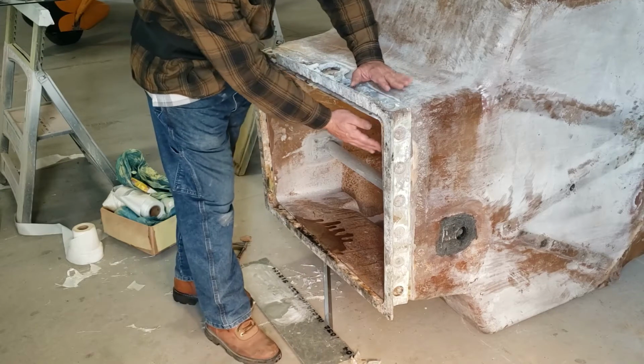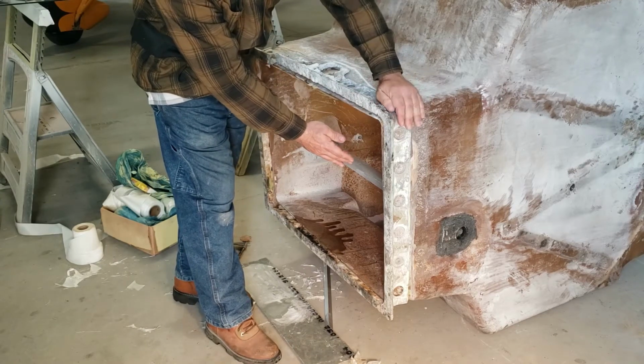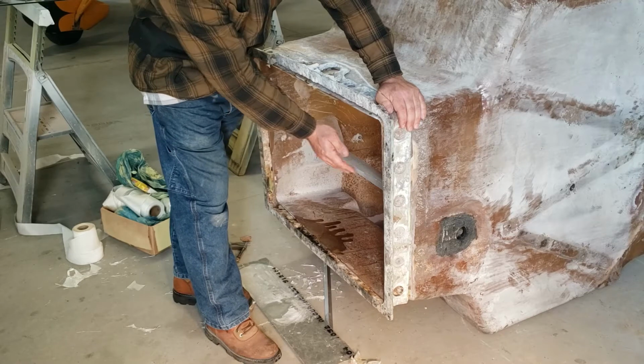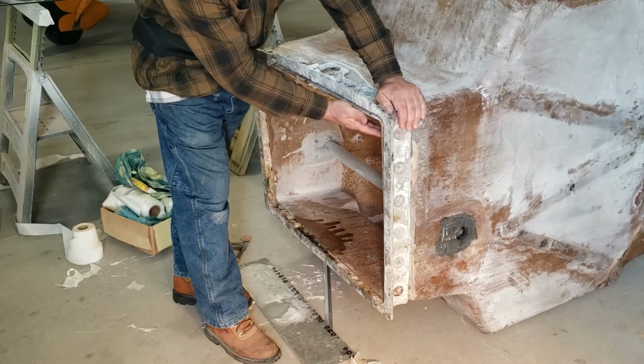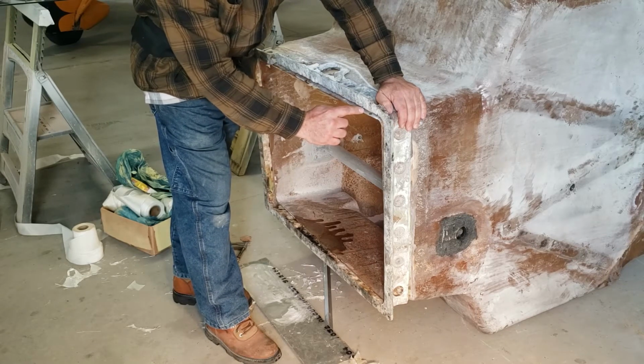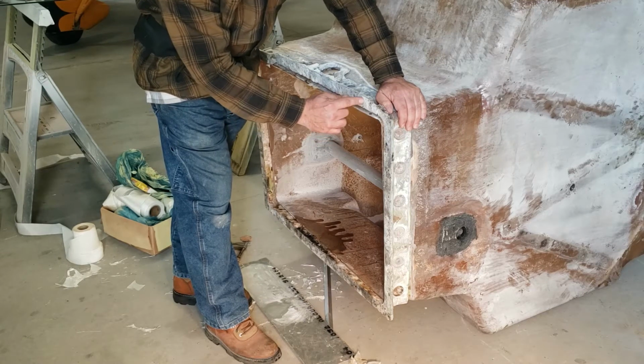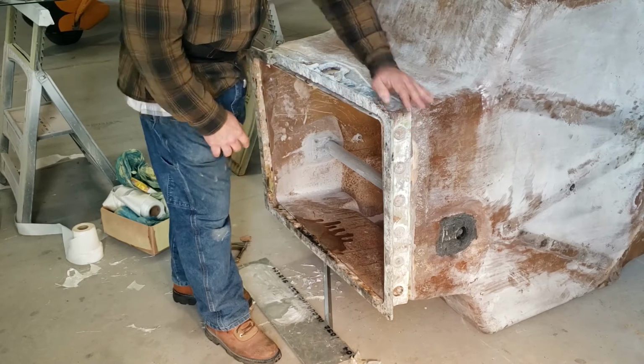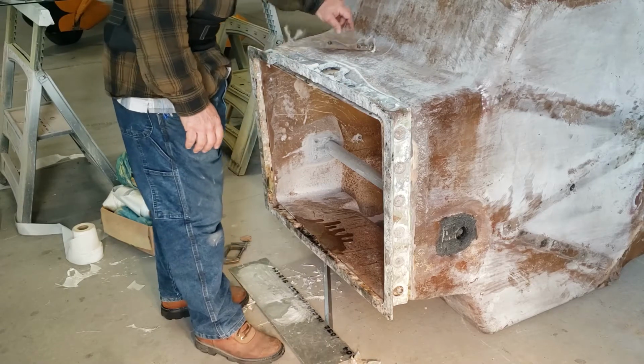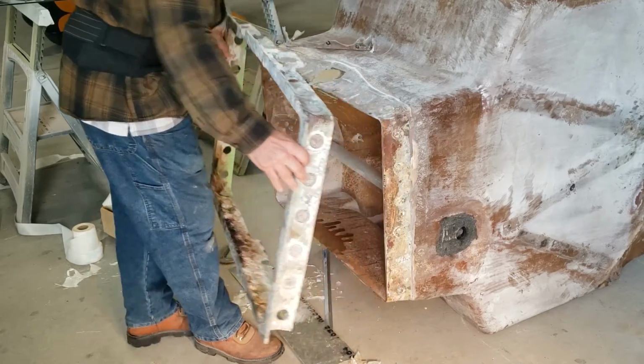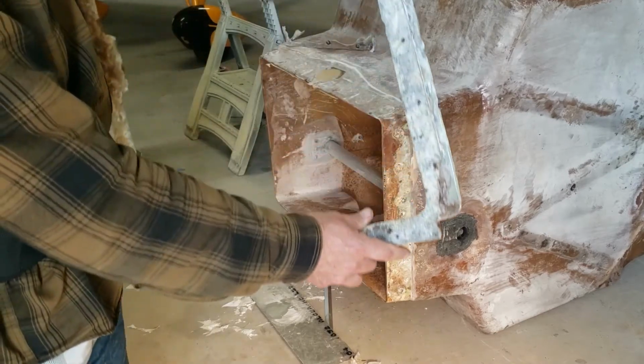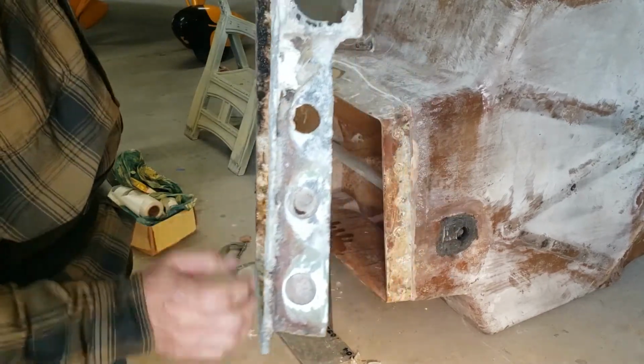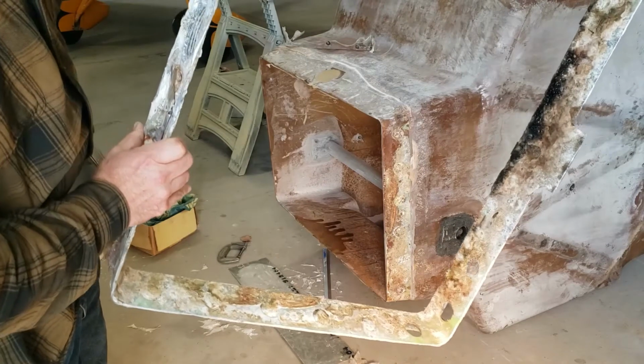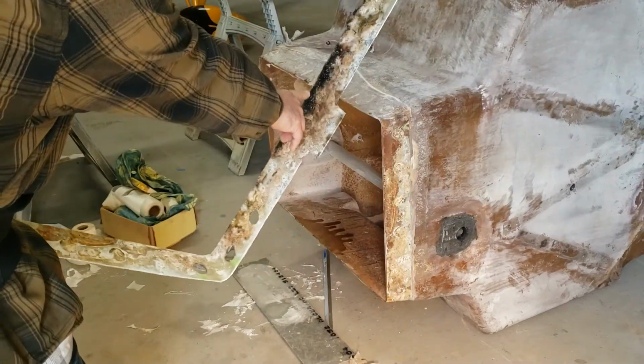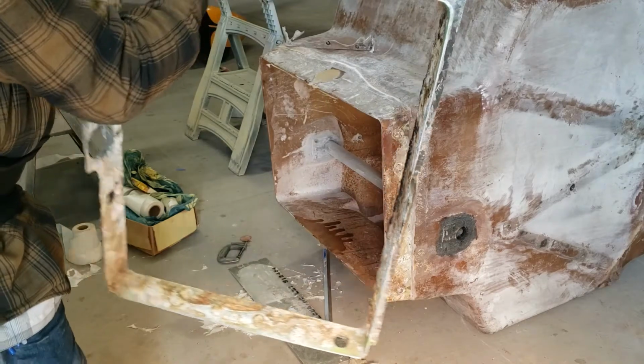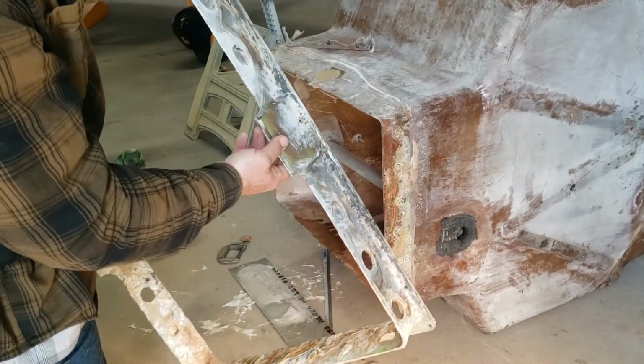So chemical on the inside, even though it was glued on the outside here where my left hand is, just like so, chemical on the inside could get underneath this lip and go up in between the layers. And once it touched this aluminum, it just started festering and growing and oxidizing. And as you can see, the condition of this aluminum is very poor. You can see here where the chemical was going up in between there. So in my opinion, this was a very poor design.